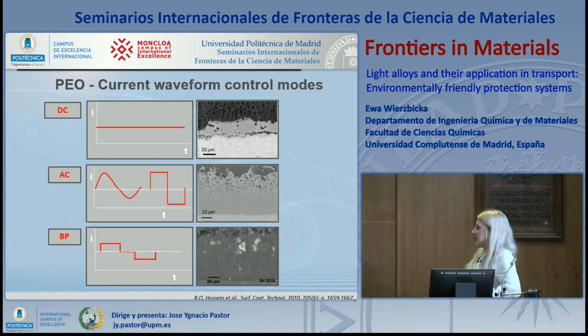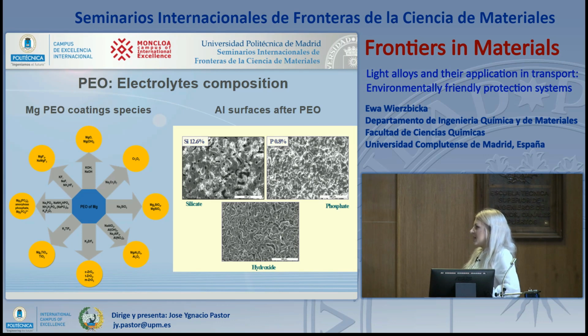PEO coatings, we can use also a similar strategy to modify the PEO coatings, like by application of different waveforms. We can get different discharges during the process, which affect the final structure of the coating. Also, we can modify the composition of the electrolyte by using varied species. We can introduce to the coatings varied phases, and also it will affect the morphology of the final coating.